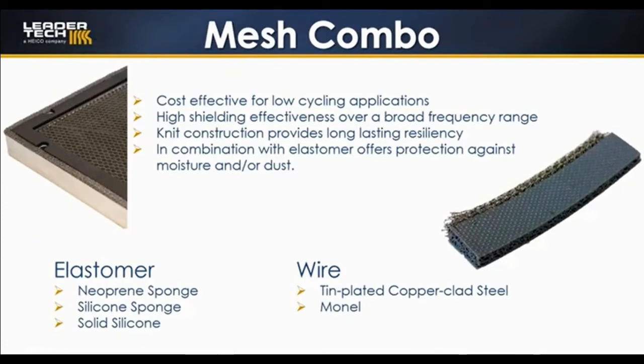Knitted wire mesh combo gaskets are comprised of Monel or tin-plated copper-clad steel knitted wire mesh, which is then bonded to neoprene sponge, silicone sponge, or solid silicone elastomer strips. They are cost-effective for low cycling applications, provide high shielding effectiveness over a broad frequency range. The knitted wire construction provides long-lasting resiliency, and the combination with elastomer offers protection against moisture and/or dust.